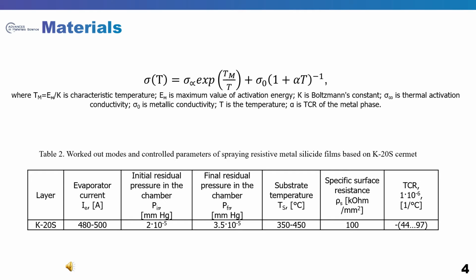However, taking into account the uncontrollability of the vacuum deposition process and the multivariance of the resistive film formation modes, it is not possible to formulate technological criteria for the controlled synthesis of thin films, the TCR of which would be close to zero in the operating temperature range. In practice, according to the selected deposition modes, the TCR values of cermet film resistors with a probability of at least 95% lie in the specified range.